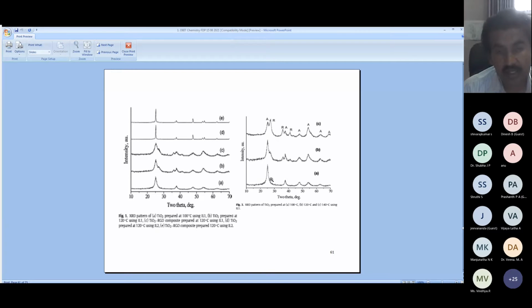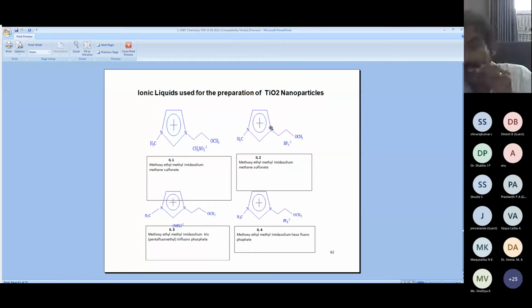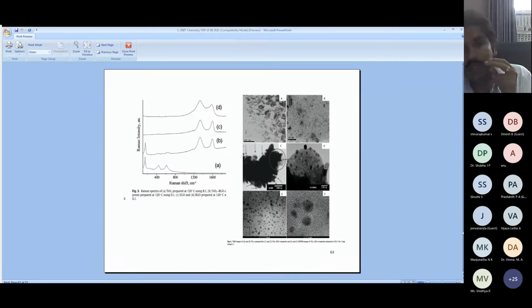When you are looking at that, at 100 degrees centigrade, we are going to get one phase. At 120 degrees centigrade, just see that there is the appearance of rutile phase, right? This is pure anatase. At 120 degrees, appearance of rutile. At 140 degrees centigrade, just see that the rutile phase increases. Let's see here, these are the rutile phase, right? As the temperature changes, there is a change of the material polymorph from one to another. Now, these are the ionic liquids we have used for the preparation of TiO2 nanoparticles.